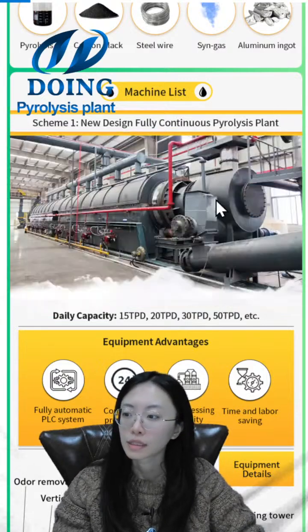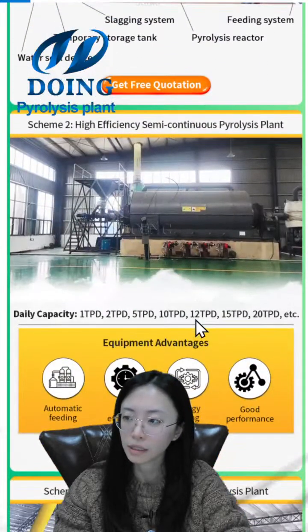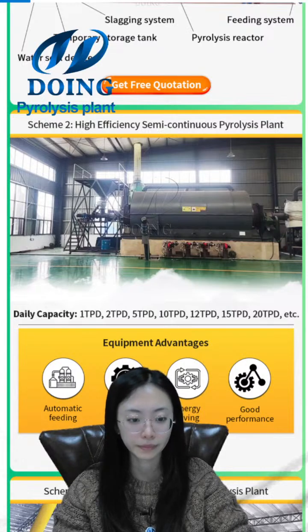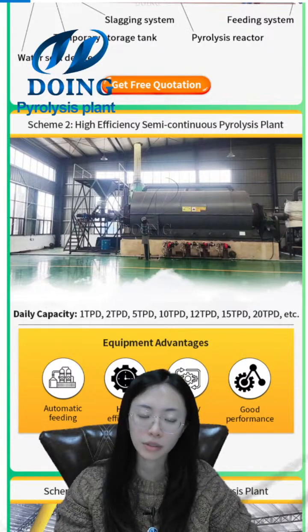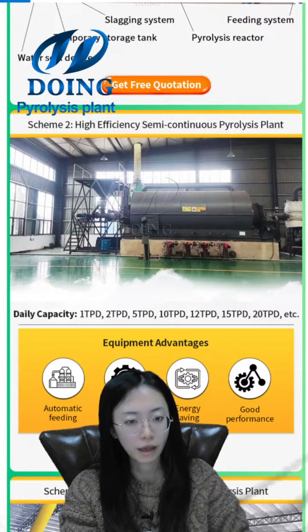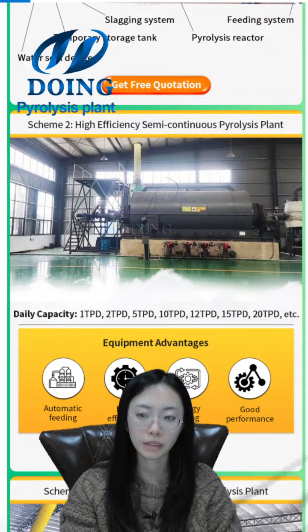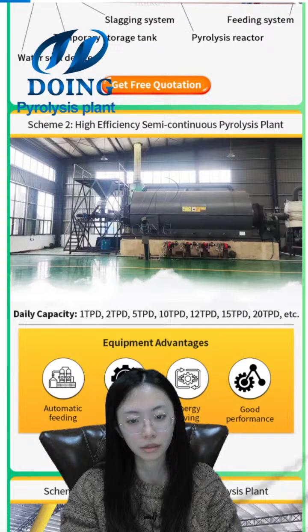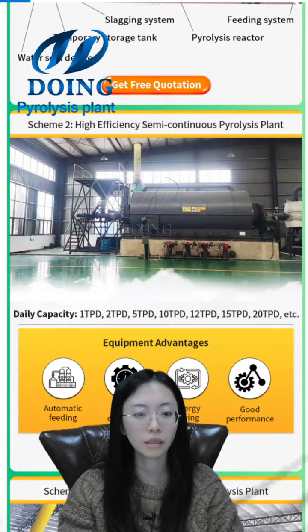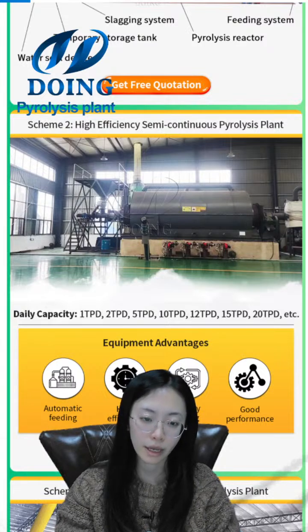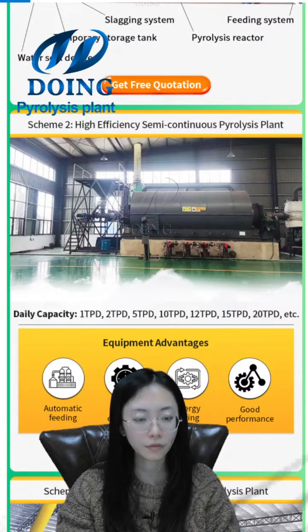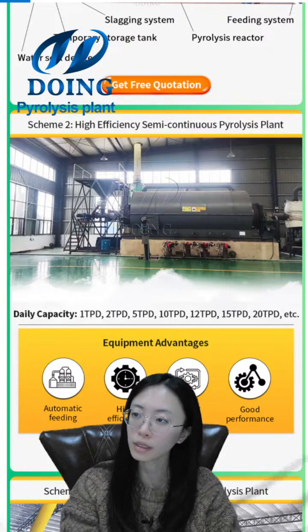Okay, and here is the fully continuous pyrolysis plant, and let's continue to introduce the configuration of the semi-continuous and batch type pyrolysis plants. In the semi-continuous one, we can get 3 batches in 2 days. They also have the technique to discharge the carbon black at a high temperature, but the steps are different. Feeding is the first step, and we open the combustion system to heat the raw material. At the same time, when it produces oil gas, we use the condensation system to condense it. After condensing all the oil gas into flue oil, we close the gas inlet. We open the slagging door to slag the carbon black at high temperature in a small reactor. This is the semi-continuous pyrolysis plant.